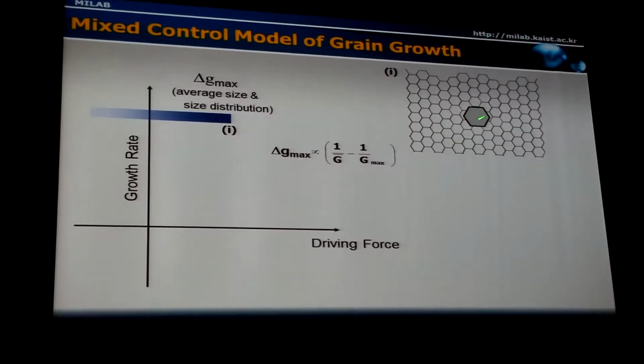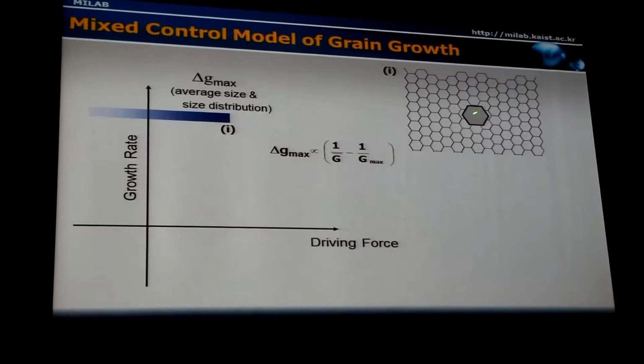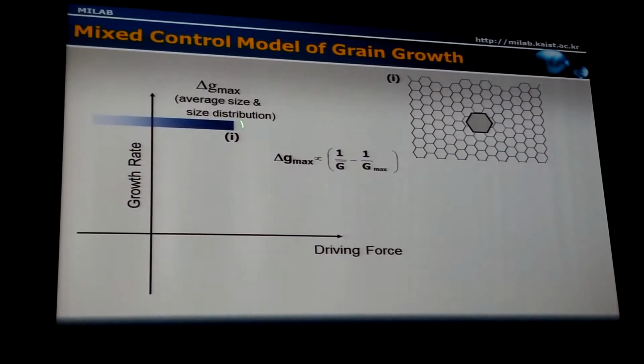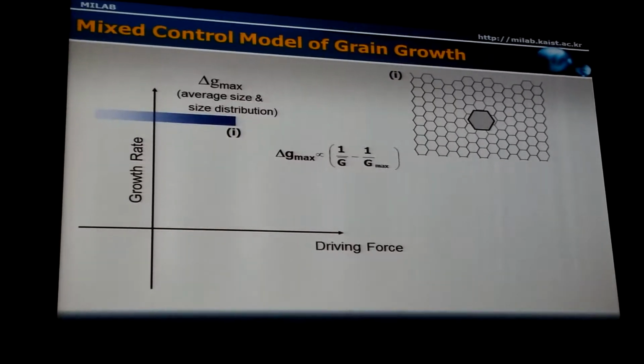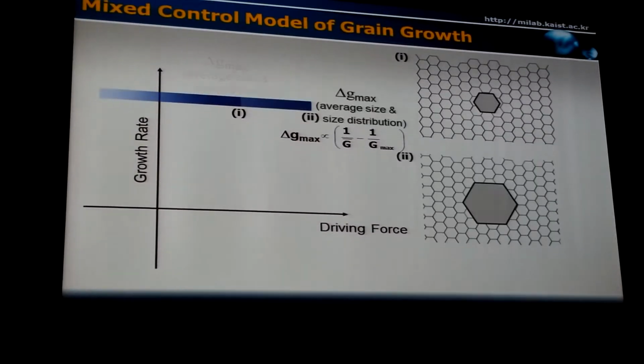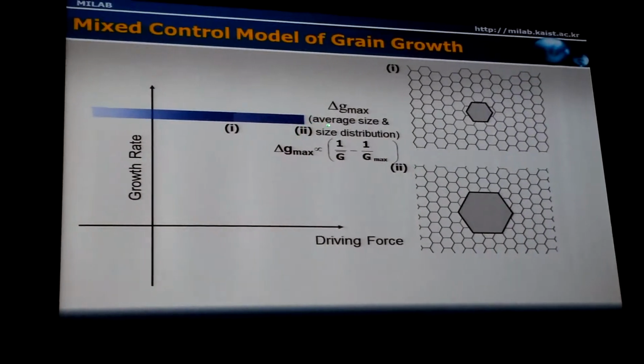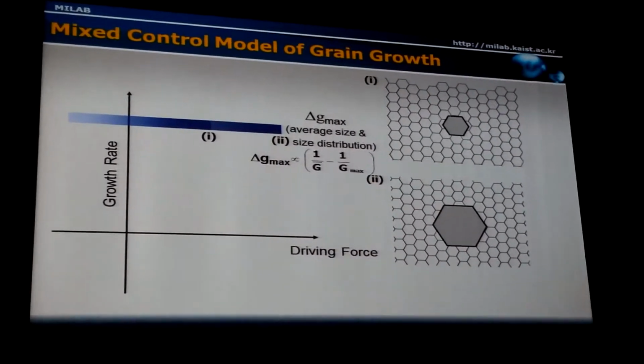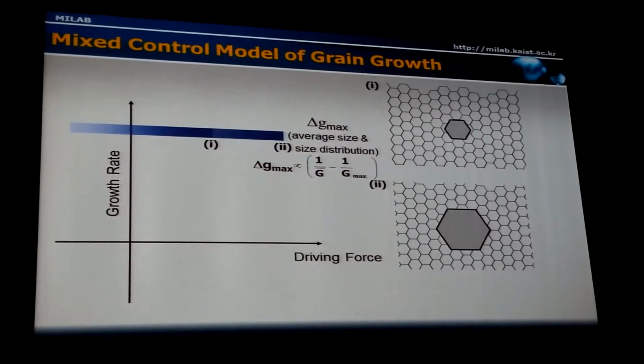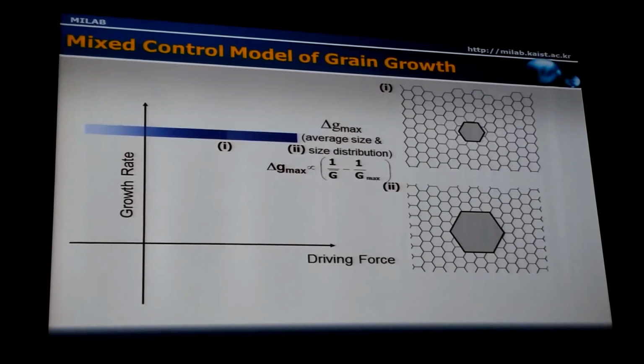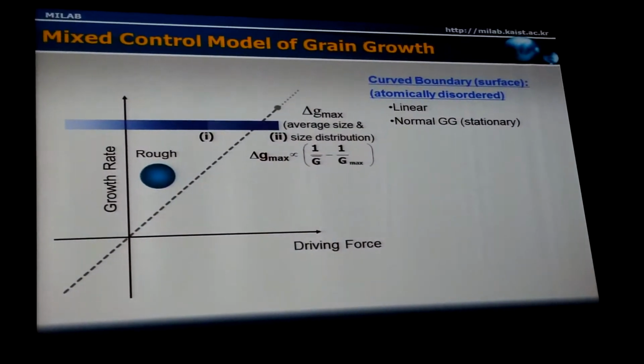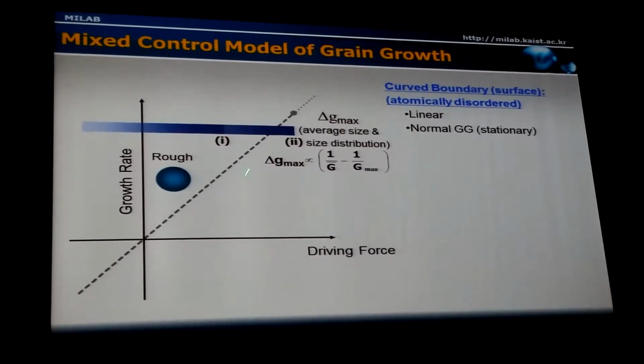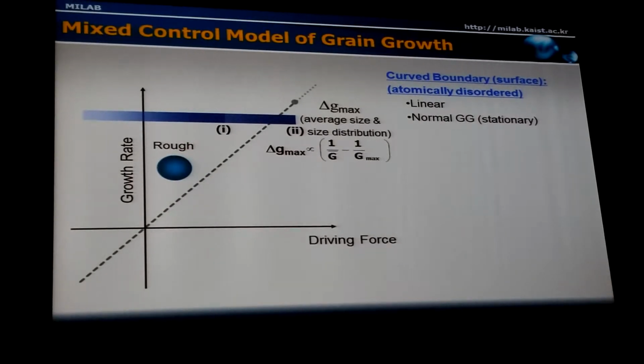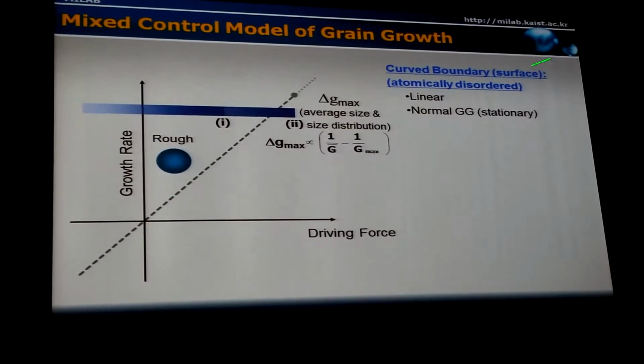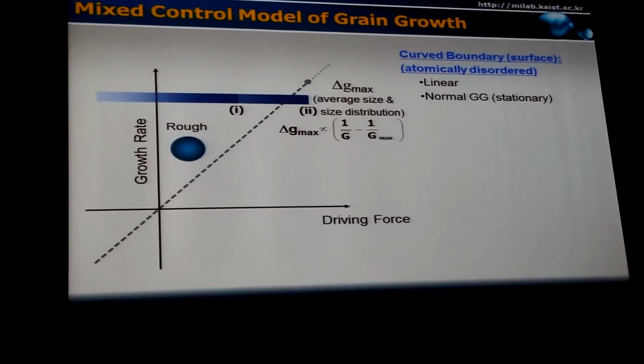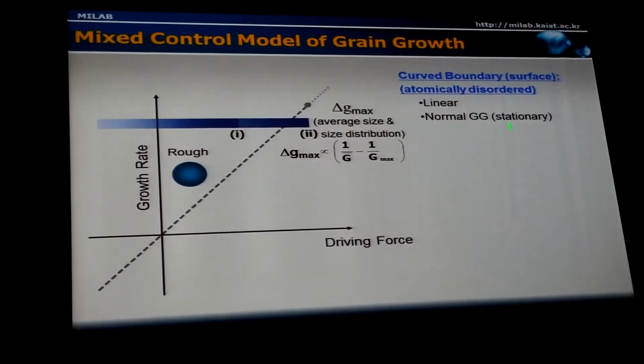So for example, in such a microstructure, this grain will have the largest driving force for the growth in the sample, and here it's schematically shown in this figure. And if the sizes of all other grains are the same, but we have a large grain here, then the maximum driving force will increase, of course. So we can change the maximum driving force in the sample by changing the average grain size and the grain size distribution. And when the grain boundary is disordered or the grain shape is spherical, in that case, the migration kinetics or growth rate is linearly proportional to the driving force. And of course, in that case, as the classical theories predict, the grain growth behavior is normal.